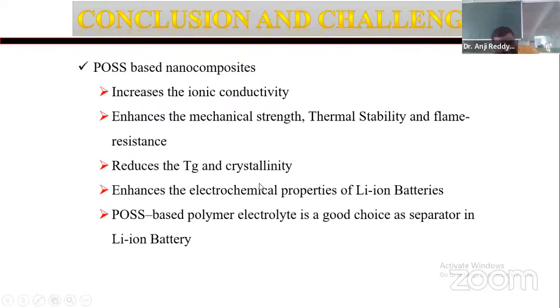And what are the main challenges? Challenges are safety only. Even though we are using POSS based materials, these are lithium batteries only. Lithium is not friendly with atmosphere; it is highly reactive in open atmosphere. Even as we are increasing the safety, lithium is still highly reactive in open atmosphere. Second thing, we need to improve the capacity. Whatever that 190, 200, 250, that is not enough for present requirements and future requirements. In future, we need to increase that specific capacity to more than 500. That is very, very important. At present, commercially, we have maximum 270 in lithium ion.